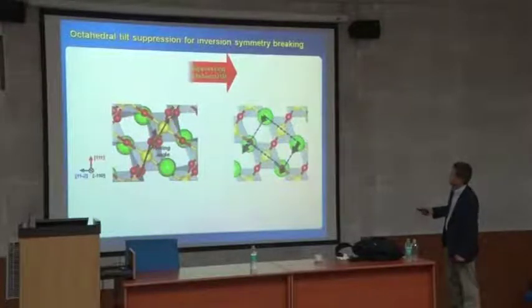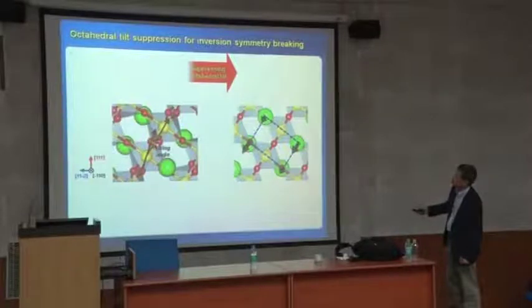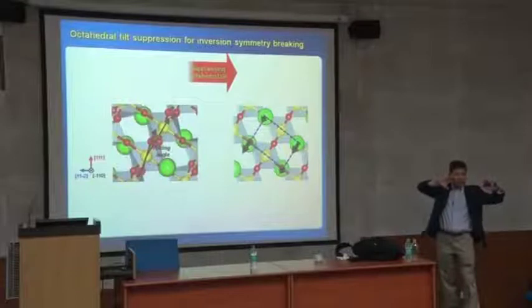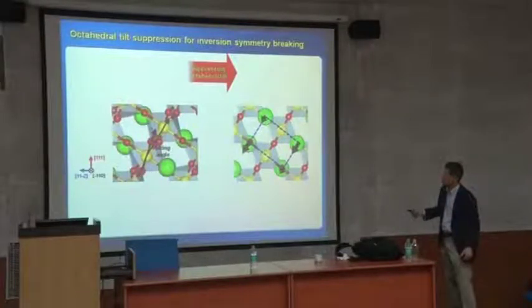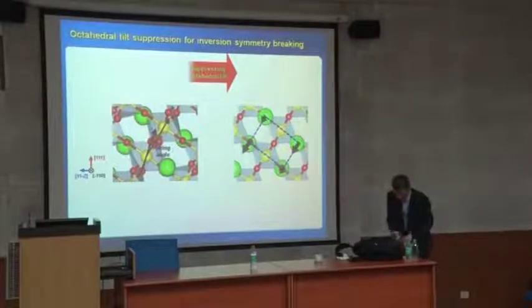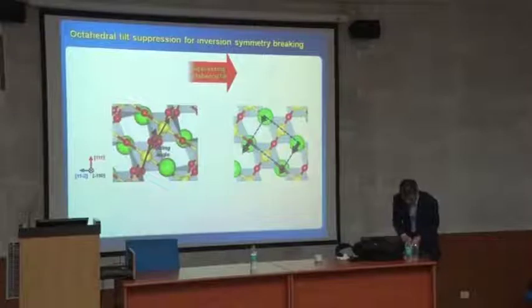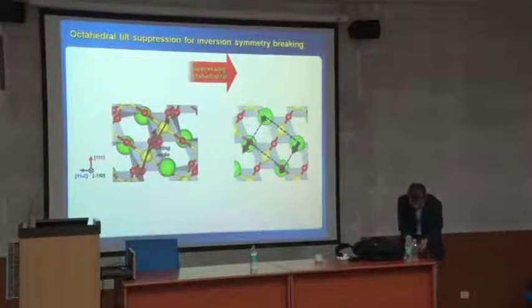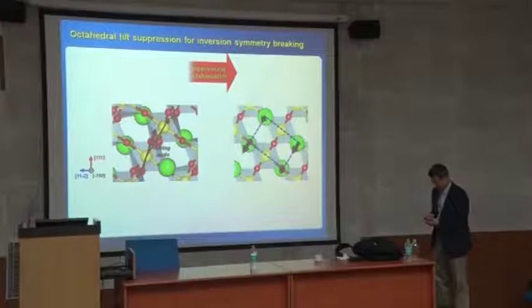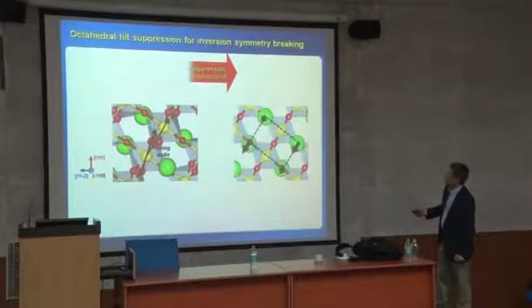And the tilting angle here is, you're suppressing this tilting. You see that tilting angle is this much of tilting angle between these two octahedra, and tilting angle is that much. Okay? So when you have the octahedral tilted that way, and this is the tilting angle. I think let me check, change this. So when you have this tilting, you suppress this tilting, and then your tilting angle here is zero.